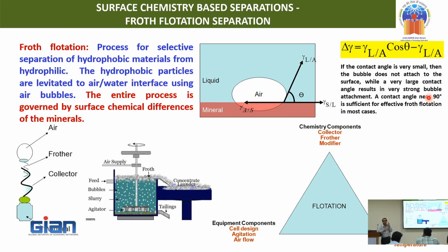So in such cases, you introduce the hydrophobicity by selective adsorption of a collector molecule. What is a collector molecule? A collector molecule is such a chemical structure which has a polar functional group attached to a hydrophobic extension. This polar end of the organic molecule will sit over the mineral because of the chemical forces between them, that can be ionic or covalent or coordinate covalent, and the hydrophobic end will give the required hydrophobicity to the surface of the mineral so that the air bubble can sit over that adsorbed material. That is induced hydrophobicity.